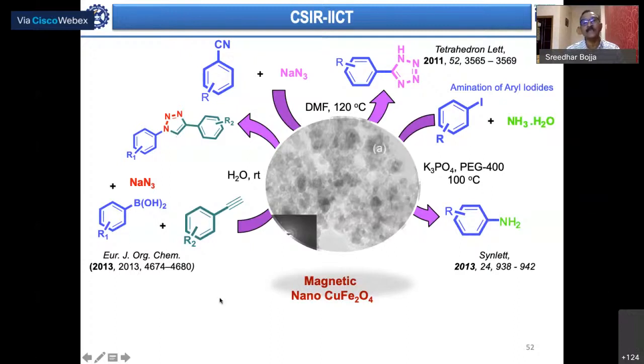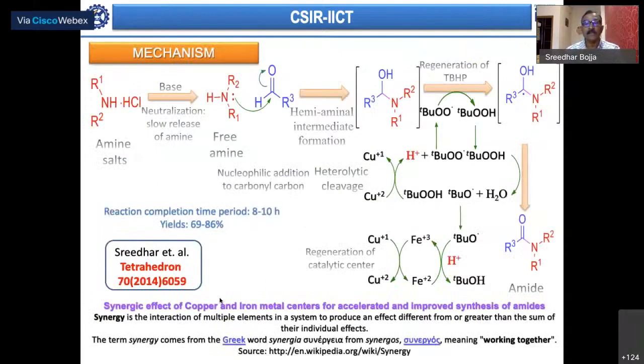And here, what is interesting to understand is the mechanism. We did the same reaction with iron oxide and followed it with copper ferrite, and found that copper ferrite as catalyst was giving better yields compared to iron oxide, which itself means there is a synergy. That is what I call the synergetic effect of copper and iron metal centers for accelerating the improved synthesis of amides in this reaction. So that synergy between copper and iron is what is making the difference. When we try to look at this mechanism, which is all known, what is interesting is where exactly copper acts as a catalyst and where exactly iron acts as a catalyst to regenerate this copper catalytic center. That is what we have to try to understand.